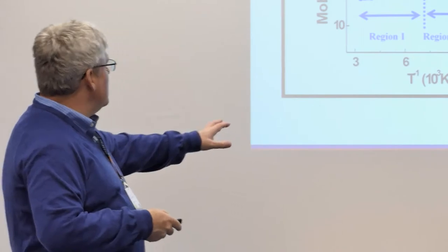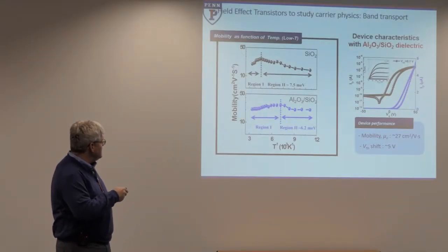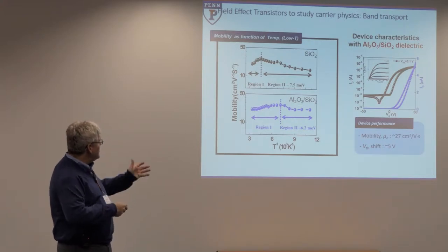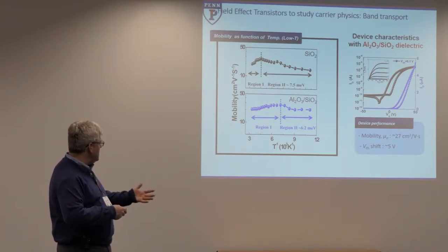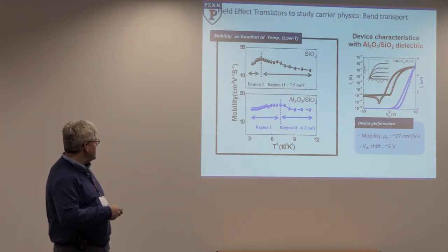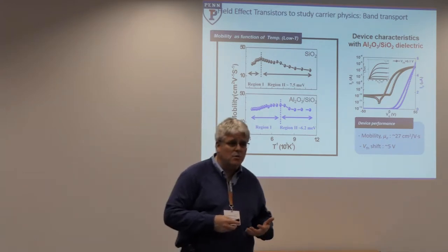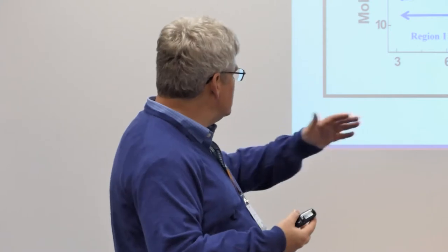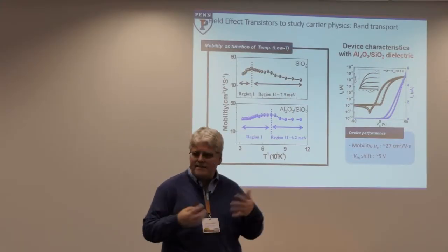With these results, the mobility goes up significantly as you go down in temperature, peaking, depending on the design of the device, at temperatures even as low as 150 Kelvin or 200 Kelvin. That shows that this really has transitioned a good portion of the transport into an extended coupled system where the particles have lost their individual character and carriers are delocalized over a number of neighbors. The mobilities in these systems are now up in the mid-30s, sort of around 30. If you do a rough calculation, that means the charge is delocalized over something on the order of about 1,000 quantum dots, a volume of roughly 10 by 10 by 10. And that really means you're getting to a point where you can think of these as a system that has transitioned to have its own emerging band structure.